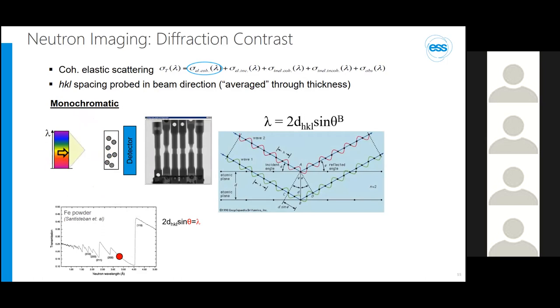If we now increase the wavelength to being two times the d spacing, then the scattering angle 2 theta becomes 180 degrees, which means we have backscattering towards our neutron source. If we now use any larger wavelengths, Bragg's law cannot be fulfilled any longer for this particular HKL lattice plane family, and we see a sharp increase in transmission. This is a so-called Bragg edge. You may wonder if this would not also work with X-rays, since X-rays and neutrons are doing the same thing. The limitation with X-rays is that at the energies this would happen, the X-rays couldn't penetrate the material of interest anymore, so you wouldn't have any transmission. So you cannot do this Bragg edge imaging with X-rays.